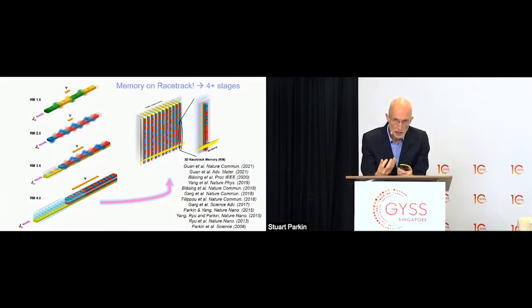So essentially, this converts the charge current into a pure spin current that carries spin angular momentum, and this can diffuse into the magnetic layer and apply torques onto the domain walls and cause them to move. And it turns out it can cause them to move much more efficiently than in Racetrack 1.0. And finally, we discovered just 5 years ago an entirely new racetrack, which is based on this synthetic antiferromagnet that